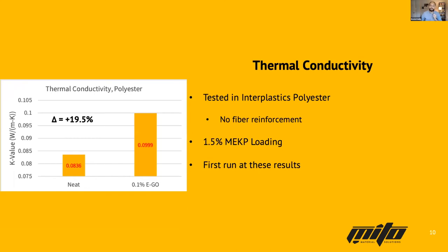Counterintuitively, we increased the thermal conductivity within polyester. We did not test this with fiber reinforcement because this was a really quick study, but this was to an ASTM standard, I think it was like C157 or something like that. We saw the thermal conductivity increase by 19.5%.